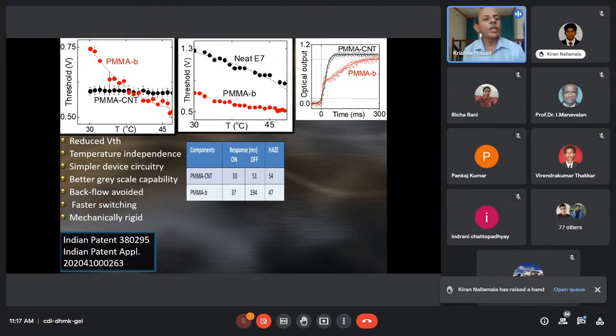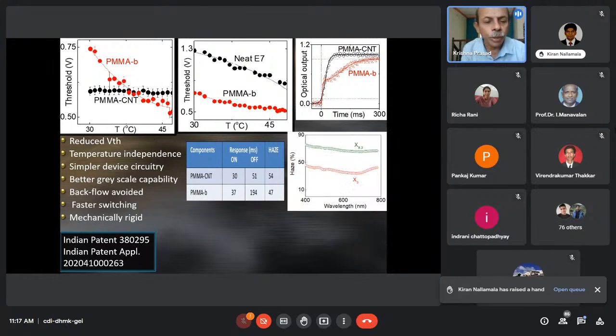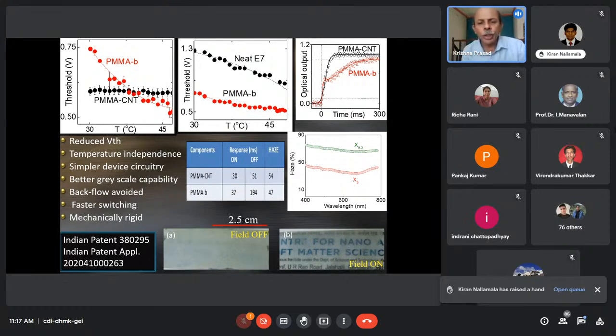So we have a plus as far as the temperature dependence of the threshold voltage, simpler device circuitry, better grayscale capability, backflow avoided, faster switching systems, and mechanically rigid ones because of the reinforcement. So there are a lot of advantages in having these reinforced systems working as polymer stabilized liquid crystals. Again, I won't go into the details of that. Just to show two pictures of the device that we created. In the field off state, you have significant scattering, so you don't see the text behind it. Whereas in the field on state, you see the text clearly because of the transparent state.